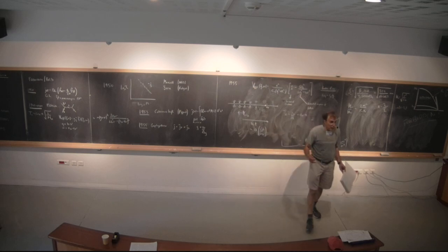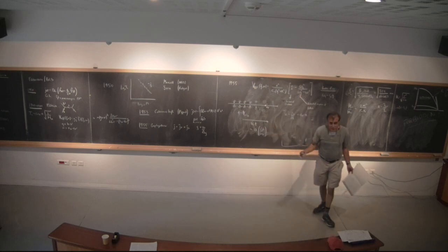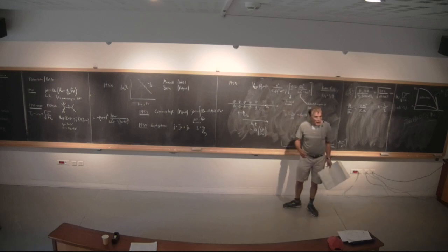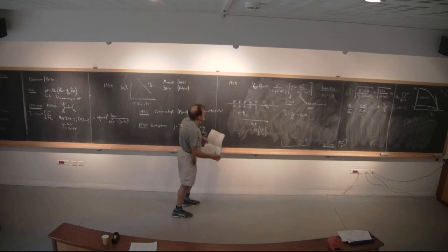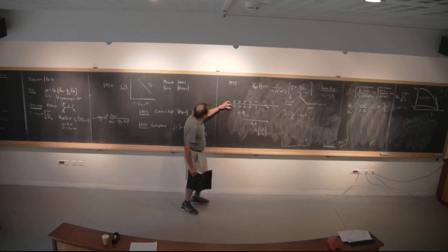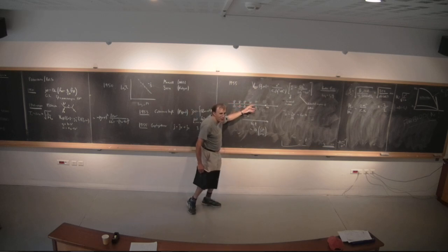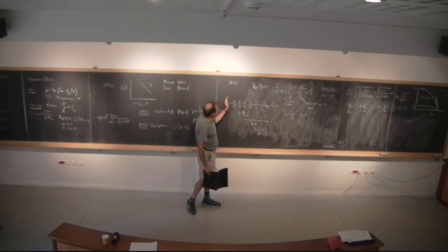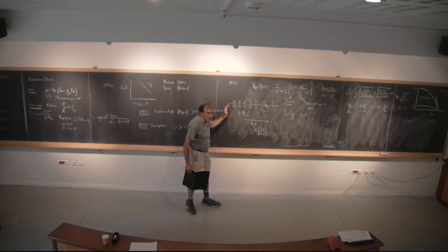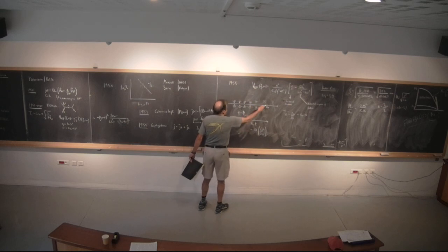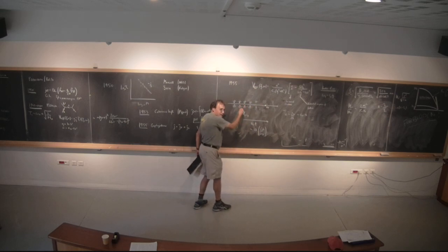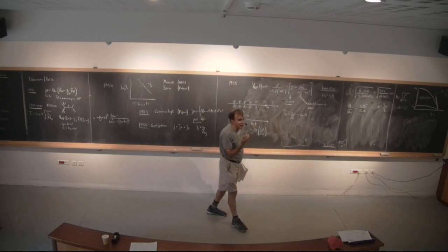Fermi energy is of the order of 50,000 Kelvin. So you've got here a safe factor of 100. Okay? So this highly retarded response is left behind long after the electron has gone by. And it's that positive background that then attracts the other electrons. Okay? And so this is the cartoon picture of where the attraction comes from as electrons go along. And of course, we now know that Cooper pairs form because another electron following after this one can feel this attraction. And they can then orbit one another as a kind of pair.